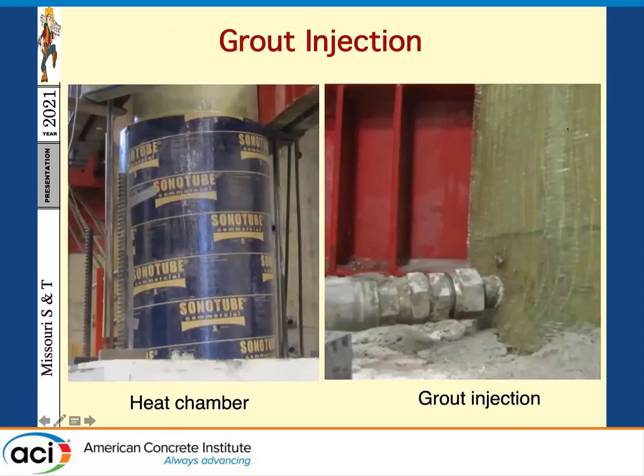So this is the FRP repair material. And here we have the hoses for epoxy injection. The epoxy was injected from the bottom of the column, and we have hoses on the top of the repair to ensure that the grout was flowing very well from the bottom to the top. The grout injection took about 1 hour.